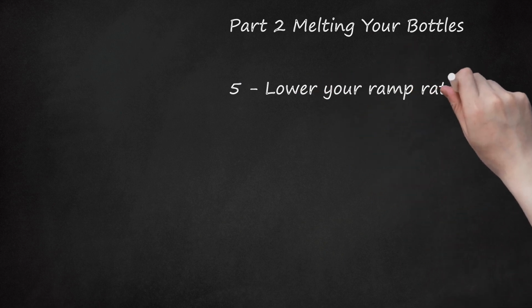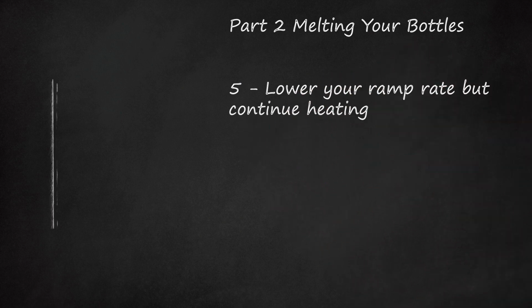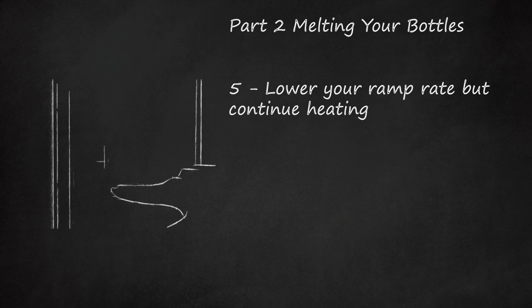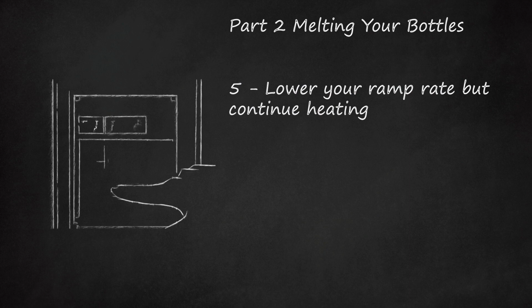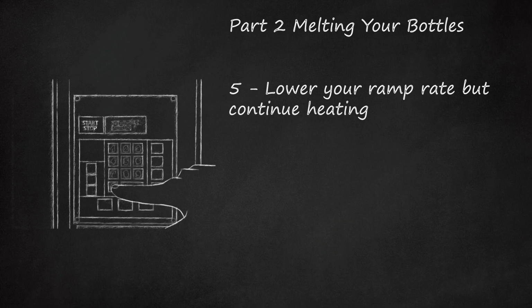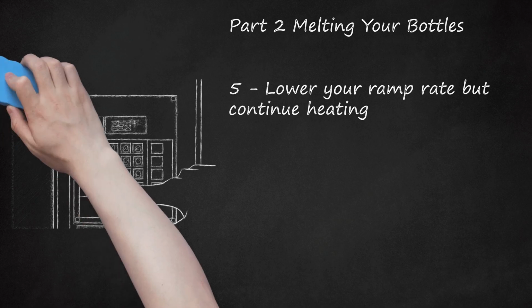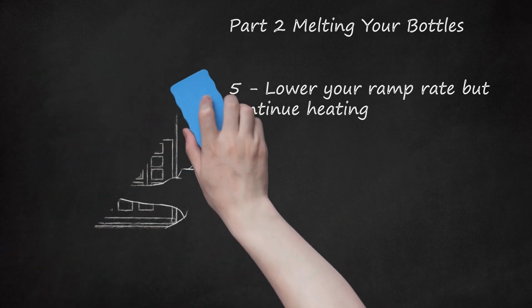5. Lower your ramp rate but continue heating. After your kiln has reached 1100 degrees Fahrenheit, 593 degrees Celsius, it should be softening the glass. The thinner sections of your bottle, like the middle parts, should begin collapsing. You'll want to keep the temperature throughout the bottle consistent at this stage for best results. A lower ramp rate of about 250 degrees Fahrenheit, 121 degrees Celsius, is recommended for this purpose. The hold time at this point will be a little longer than preceding hold times. This longer hold time gives the temperature a chance to equalize.